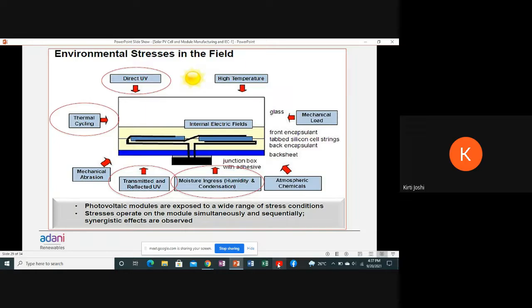Then mechanical abrasion. On the backside there is a possibility of abrasion due to high wind conditions or some high storm condition, windstorm condition. Abrasion on the back sheet is possible. Then transmitted and reflected UV, ultraviolet rays, then moisture. Moisture is the major factor for the degradation of the module, and atmospheric chemicals. If there is a very polluted atmosphere, then the degradation rate is high.